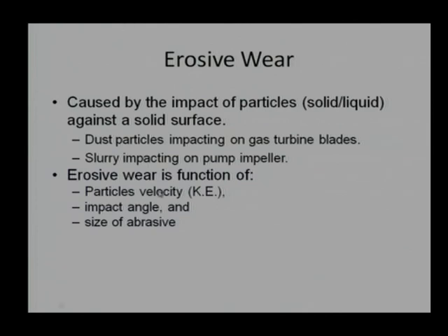We can say the erosive wear is a function of particle velocity, because we know the kinetic energy depends on velocity, and this is a strong tendency. It depends on the impact angle, the angle at which the particle is going to hit the surface. We know from the momentum point of view that this angle will decide how much energy is getting transferred from the particle to the solid surface. So, impact angle is important for us. And last, what is the size of the particle? Is it the low size or the high size? We know size is related to mass, and mass is related to kinetic energy.